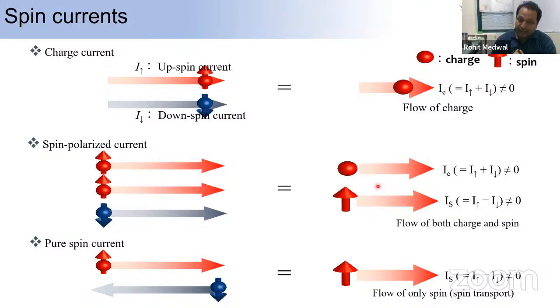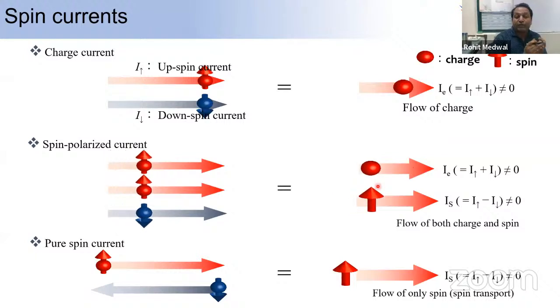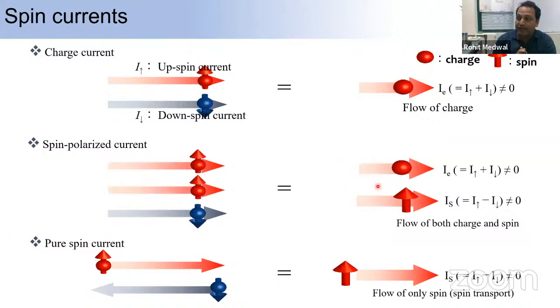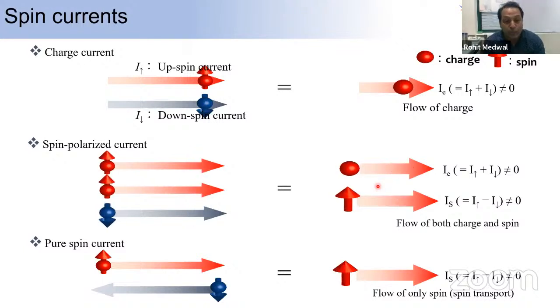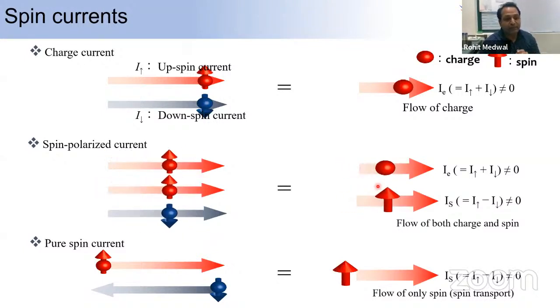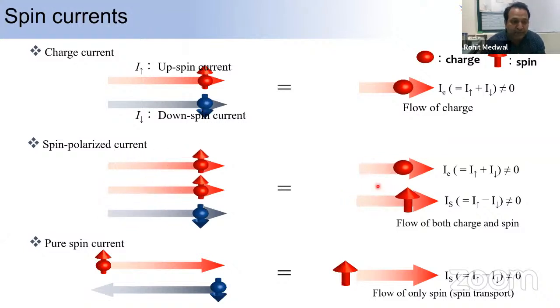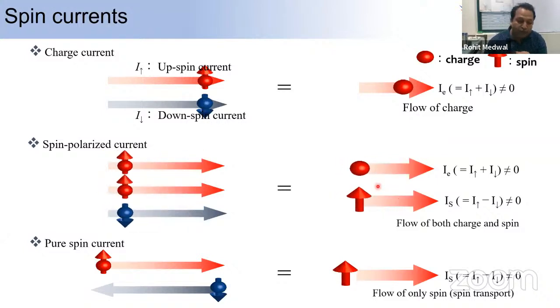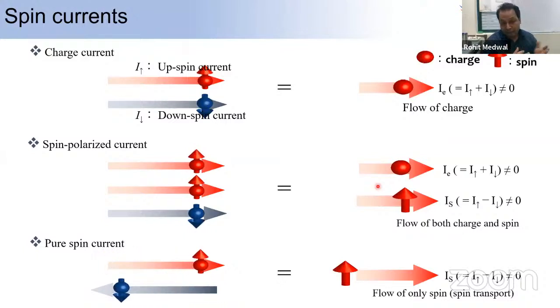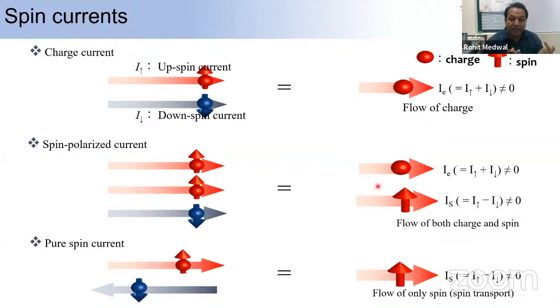What about the pure spin current? When this charge current is passed through unique materials called spin Hall materials, where the spin orbit coupling is very high, or you can say because of the relativistic effect of the spin orbit coupling in the material, we observe two different channels of spins: the up spin goes in one direction and the down spin goes in the other direction. This is what we call the pure spin current. There we don't have any charge current flow. We only have the propagation of angular momentum, which we call the pure spin current, or simply the flow of angular momentum in quantum mechanical terms.